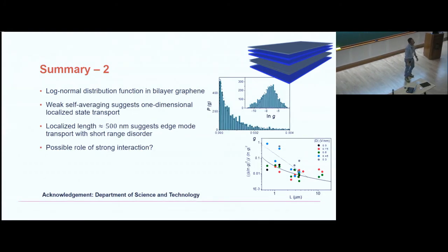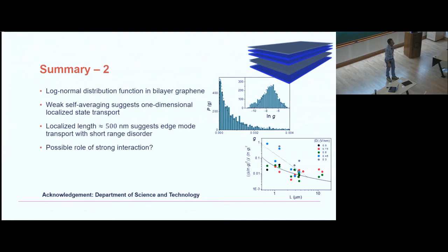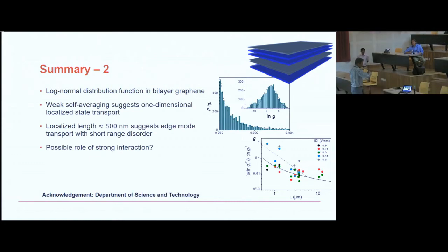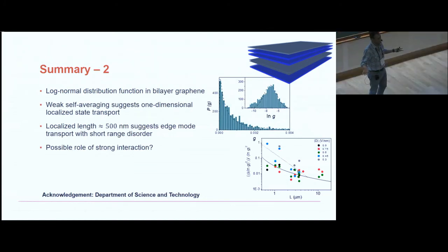For the quantized conductance measurements, can you measure a subband spacing by taking finite bias data, or is this too fast of a process when you stretch it out? So that's a great question. As a matter of fact, if we go to different conductance levels and do the non-equilibrium spectroscopy, there is no subband spacing, because there is no subband apart from the edge. There's only one mode along the edge. So we do not see the standard features of peaks coming in and going up, or band splitting. Those features are completely absent in these kinds of systems because there is just one mode. So no, the answer is we do not see any subband spacing.